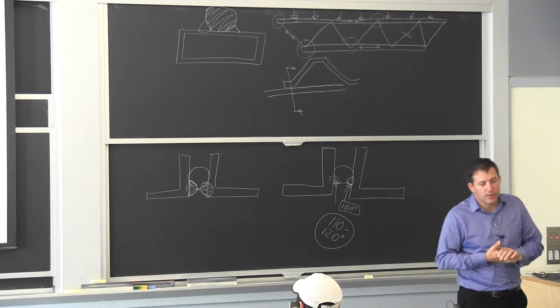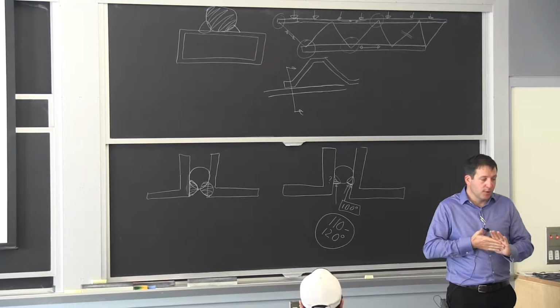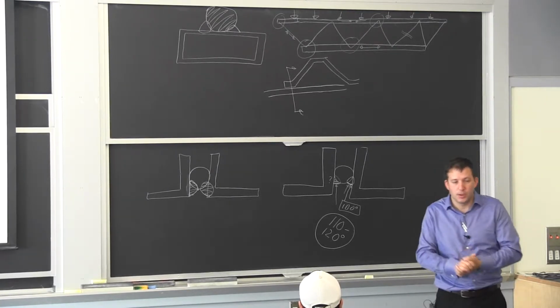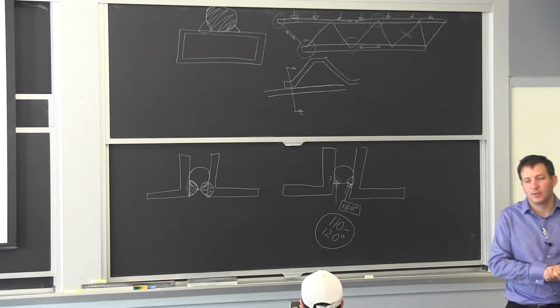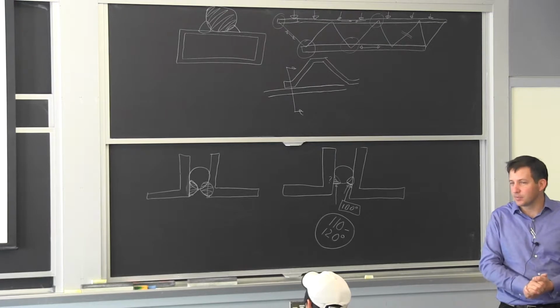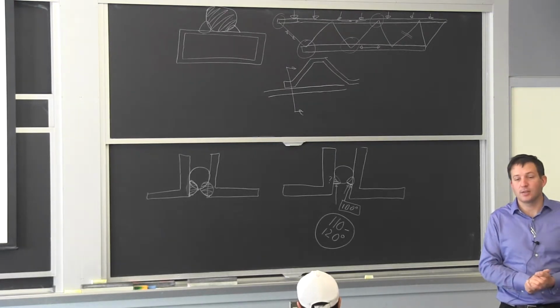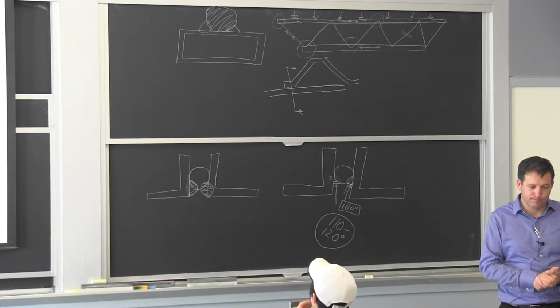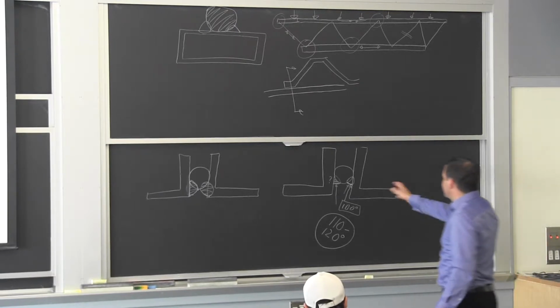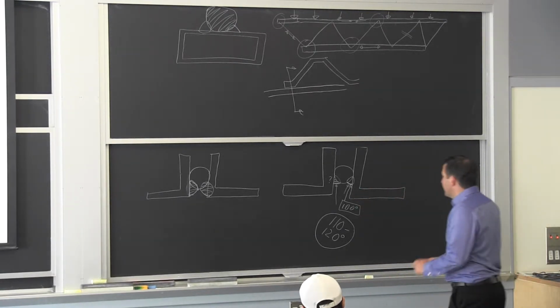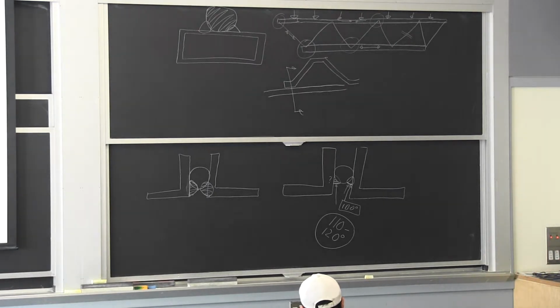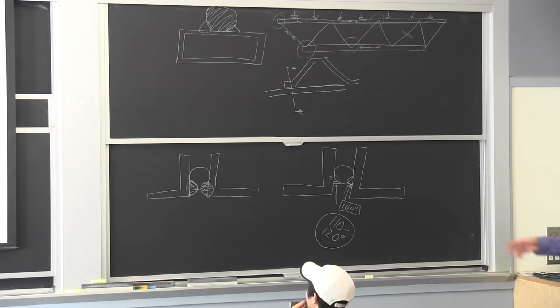What I've shown both on Friday and today is the importance of looking for fusion. The codes will say lack of fusion is not acceptable, and then it becomes on the shoulders of the inspector to determine whether you had it or not. It's very hard to verify it, especially when you're looking at these complex joints. There are a lot of non-destructive techniques using ultrasonic, using magnetic particle that will tell you on a groove weld and a nice flat weld if you had a problem or not. But when you're looking at a little detail like this, it's very difficult to come with a tool and see if you had fusion or not. So it's becoming more of a visual criteria, looking at the angle.